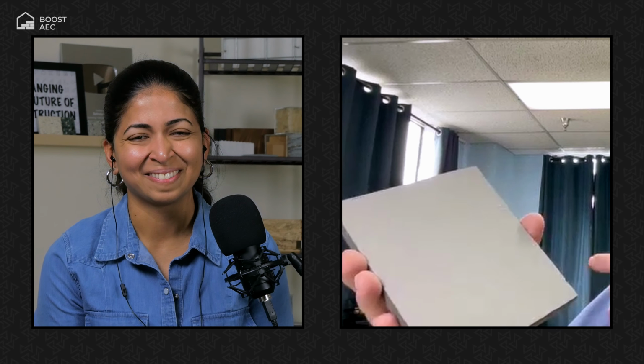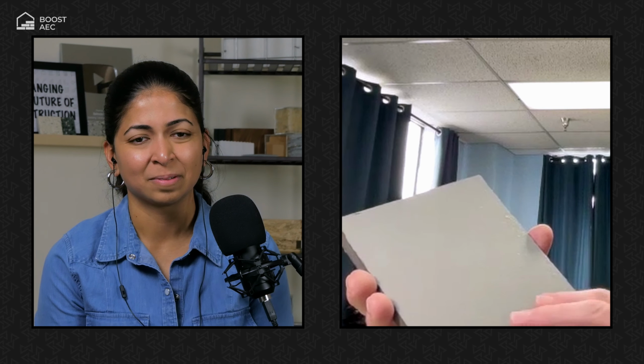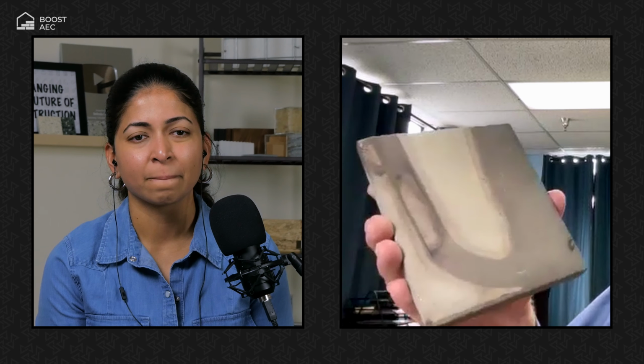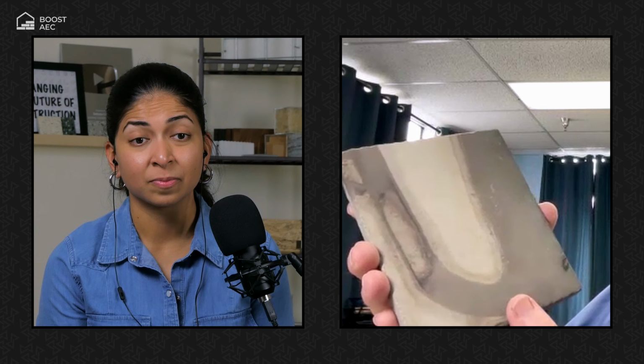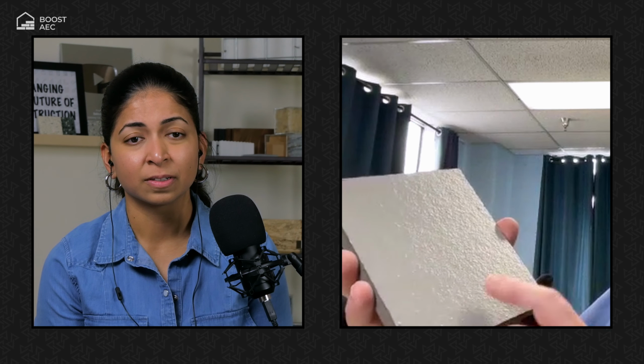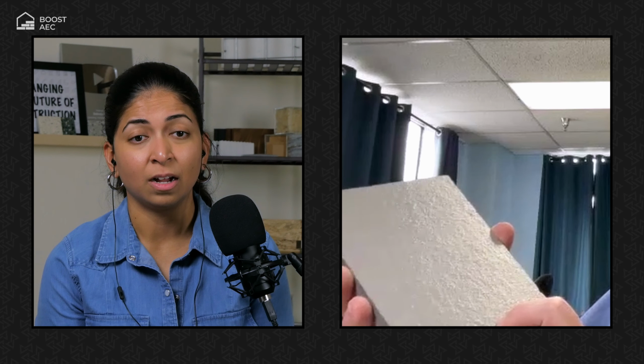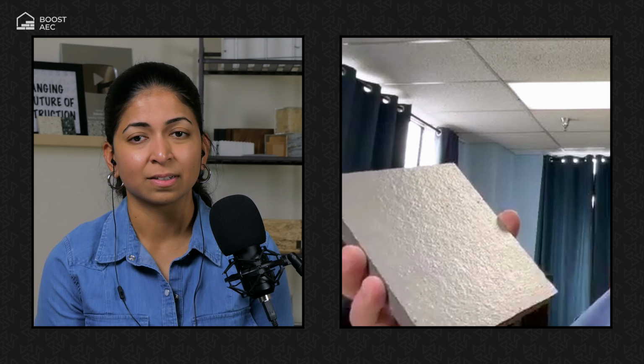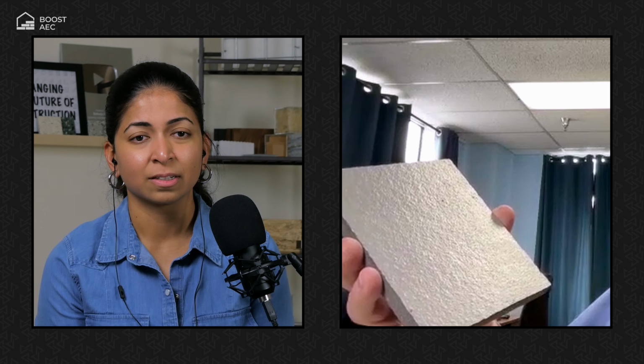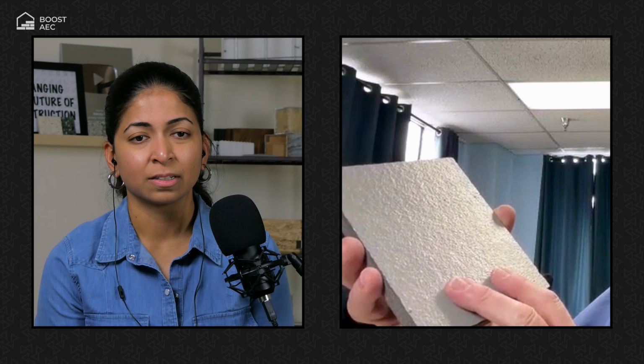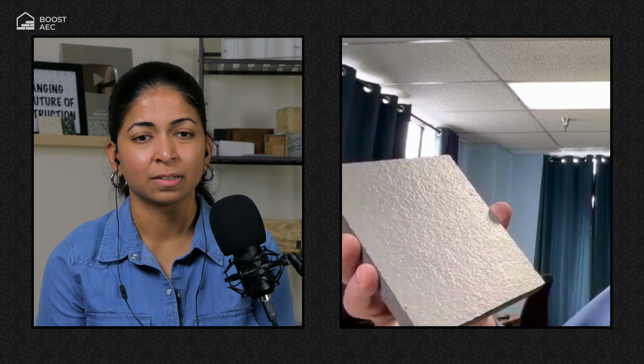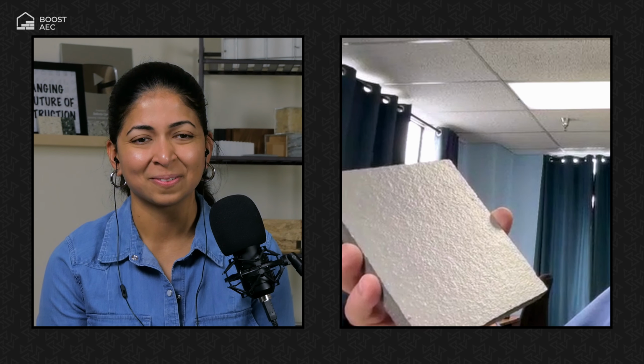And that was something epoxies of that type hadn't done before. It had not been done before. So when you're looking at technology like this, can you raise it up, please? Yeah. Okay, perfect. So when you're looking, this is called Composite Coat XD. This particular sample has been sat in food acid, and there's an abrasive scrubber pad that's been over this 100,000 times, and there's no damage. And that's because it's molecularly bonded into the concrete, and it has a hybrid organic, inorganic top coat that's chemically bonded into the ceramic guard itself, right?